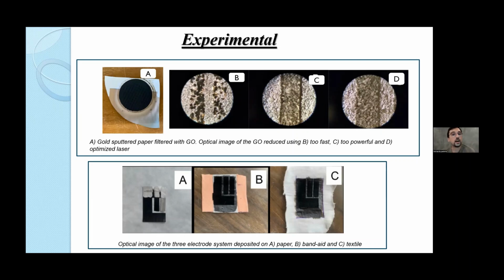So we have used an electrode made of graphene oxide, a reduced graphene oxide, supported on paper. Now I will say why we chose paper. So the experiment started from a standard Whatman paper. It has been filtered with different amounts of graphene oxide, and then using a carbon dioxide laser, it has been reduced back to graphene. This is a very important aspect of this work, because simply by tuning the parameters of the laser in terms of speed and power, it is possible to obtain different kinds of electrodes.